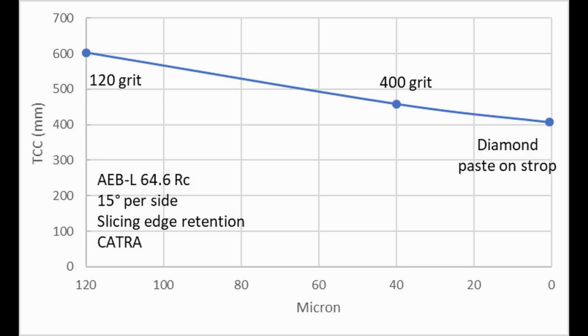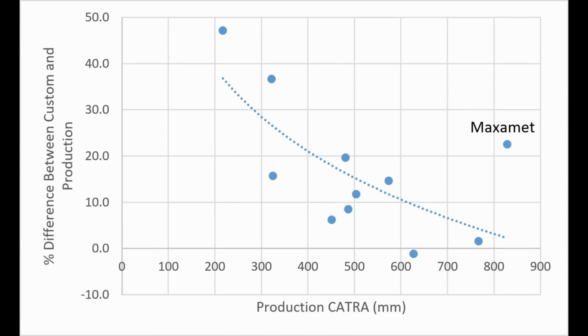So I did a study on this a long time ago. I compared a 120 grit edge to a 400 grit edge to a diamond paste-on strop polished edge, and the more polished the edge, the lower the edge retention was for a slicing test, which Catra is. Another clue as to where the differences are coming from between my custom knives and those factory knives, we can see on this chart. So I have the production Catra knife measurement versus the percent difference between my knives and their knives. And you can see that the higher the edge retention, the less difference was seen, with the exception of Maxamet, which appears to be an outlier.